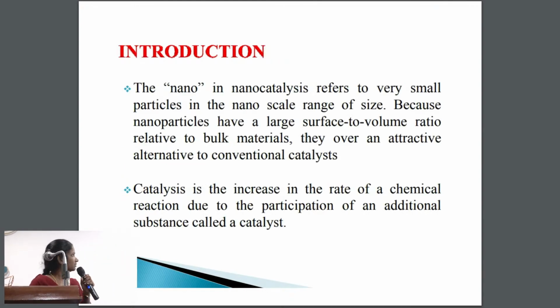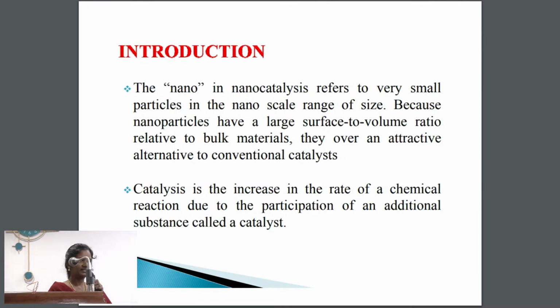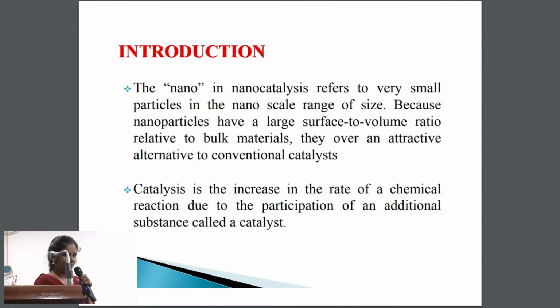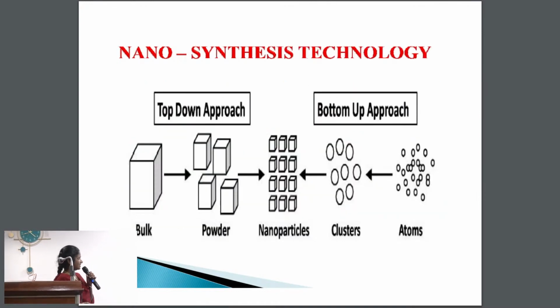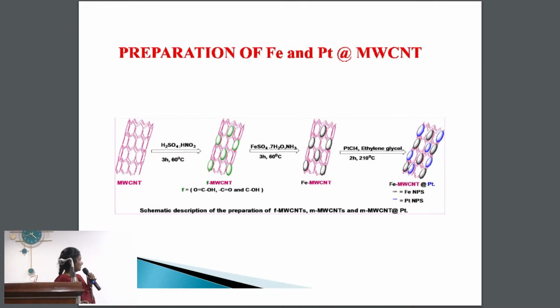Nanoscience is the study of fundamental principles of molecules and structures with at least one dimension in the nanometer range. This is the nanosynthesis technology. Preparation of iron and platinum decorated multi-walled carbon nanotube. First, I functionalize the multi-walled carbon nanotube using sulfuric acid and nitric acid in a 3:1 ratio for 3 hours at 60 degrees Celsius, creating functional groups such as carboxylic and hydroxyl groups.